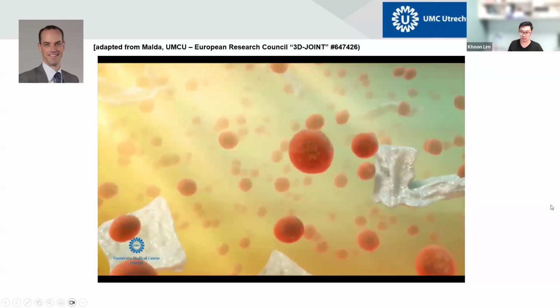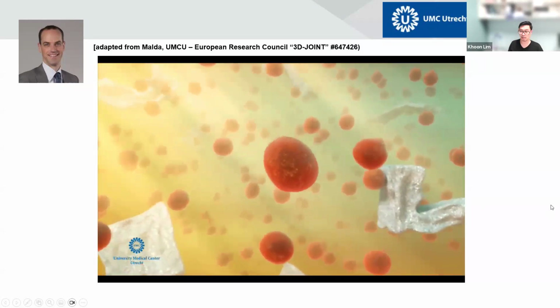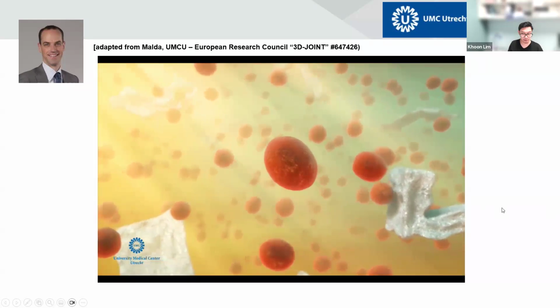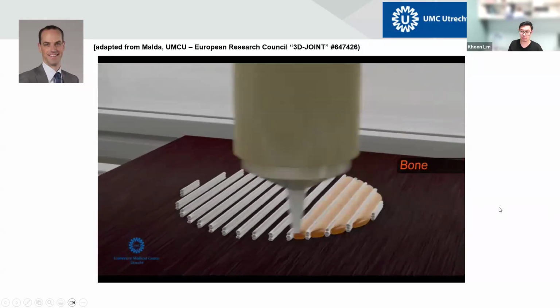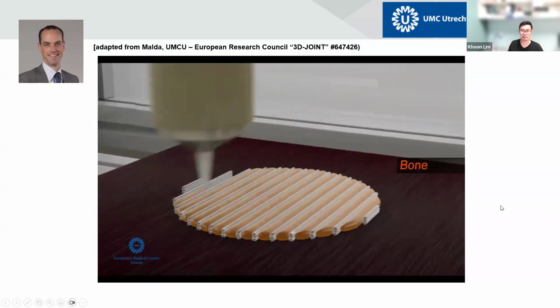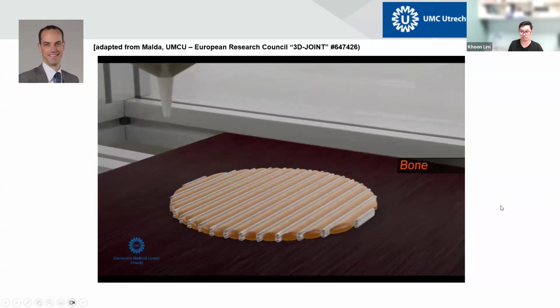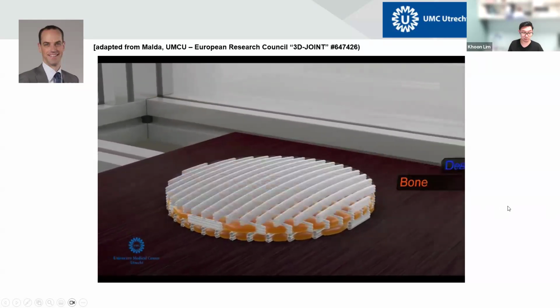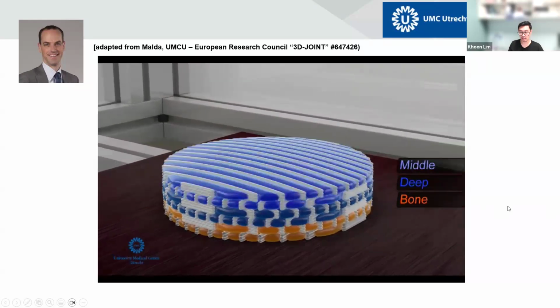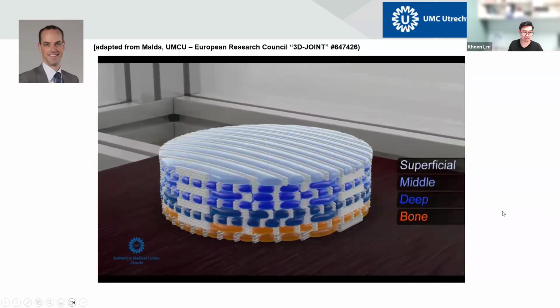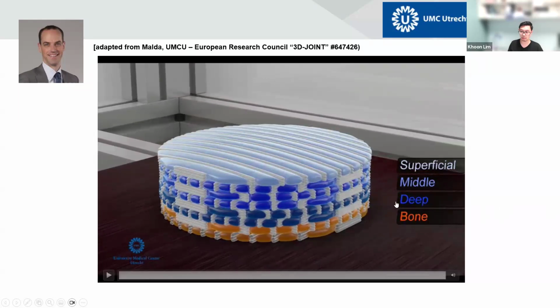So this is a bone bioink. Within the bioink, you have the cells of interest. So it can be mesenchymal stem cells with growth factors of interest like BMP2, BMP7, for example. And you can start printing them in a layer by layer fashion. So you first start with your bone layer, and then your cartilage layer. And even within the cartilage layer, you can have different zones. You can have your deep zone, your middle zone, and your superficial zone.